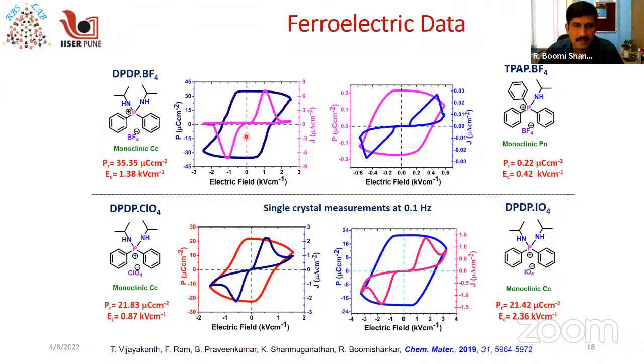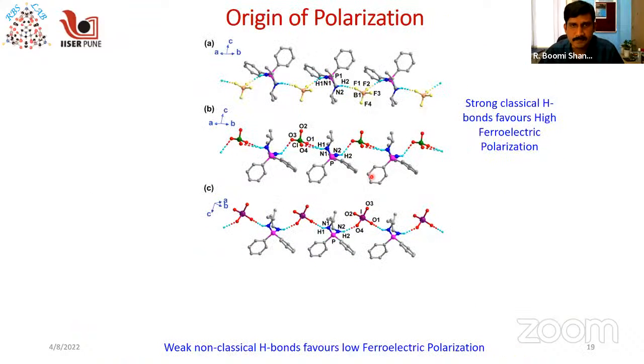Of which 3 of them show very high polarization attributes, which is around 35 microcoulombs, 21 microcoulombs and 21 microcoulombs and so on. One of them, although ferroelectric, shows a very low ferroelectric polarization, which made us look into their crystal structure. So of all the diphenyl diisopropyl system, it forms a 1D hydrogen bonded assembly mediated by strong classical hydrogen bonding interactions along the polar B axis.